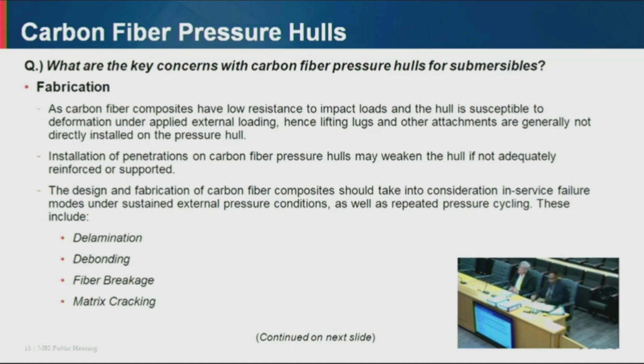Okay. So when you design your carbon fiber pressure hull, you also need to consider various failure modes, including delamination, debonding, fiber breakage, and matrix cracking. Delamination means separation of the carbon fiber plies. The plies start separating. Debonding means the carbon fiber strands start coming out from the epoxy matrix. Debonding is caused by failure of adhesion between the strands and the epoxy matrix. Matrix cracking is characterized by cracks in the epoxy matrix, and this occurs due to fatigue of the material. Fiber breakage occurs when the carbon fiber strands snap or break. This can be caused by high stresses, impact loads, or manufacturing defects in the carbon fiber. Since the carbon fiber strands are the main load-bearing member in the composite, if you have strands that break off, the strength of the hull will deteriorate, and you can have premature collapse of the pressure hull. Okay.